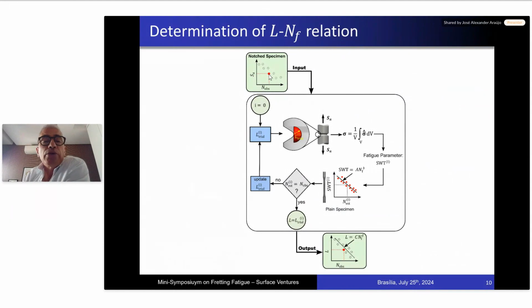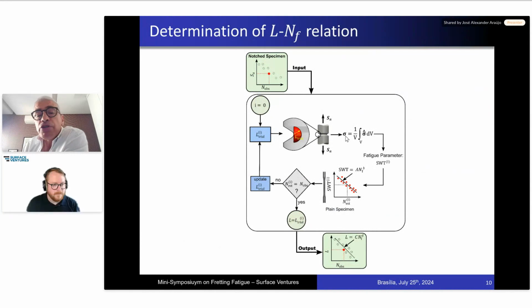Let's choose this red point. This red point has a nominal amplitude of stress that is developed during the test, and this will correspond to our observed life, the life for failure of the wire. So it's a test in a wire like this one with a V notch here. We apply this nominal stress at the top. We have a finite element model running together with this problem. Then we guess the size of this process zone at the beginning. We integrate, get the average stress tensor within this process volume. And then from this average stress tensor, we compute the Smith-Watson-Topper parameter.